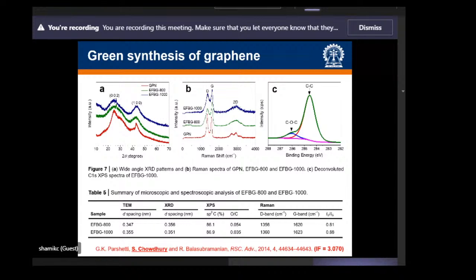And although the EFB biomass also contains other elements such as nitrogen, sulfur or phosphorus, the lack of any additional spectral peaks actually suggests that no significant level of elemental impurities was present. So this confirms the near pristine composition of the EFB derived carbon samples. Okay. And what else did we do?